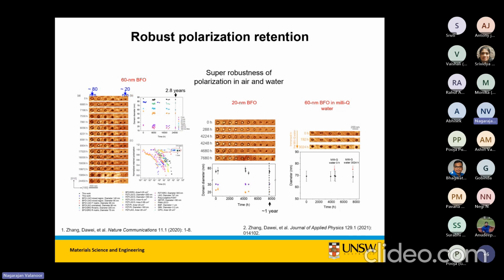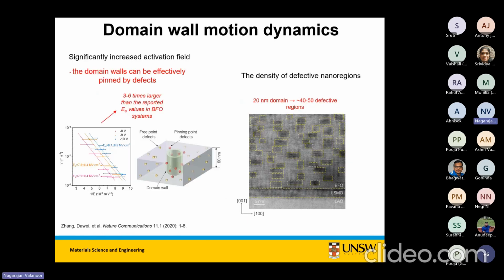Okay, so I can tell you now the paper was written completely in a reverse engineering manner. We found the bits written, we were like, wow, the bits are still written, why are they written? And we found that the defect stabilized. So this is a really nice example of why we call it designer defect. The defects are somehow a positive attribute, like I'm a designer defect. It's not like, oh, gee. And you can see that there's clear diffraction contrast. There's quite a bit of this. And we have a follow-up paper coming where we completely analyze the crystallography of that defect.